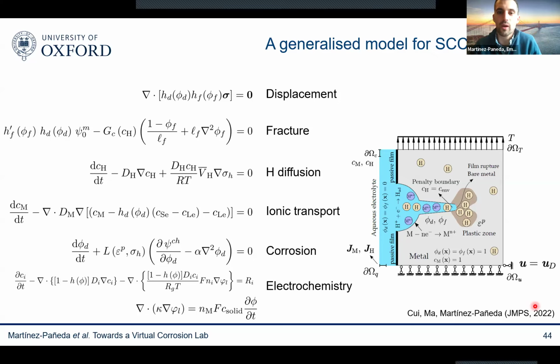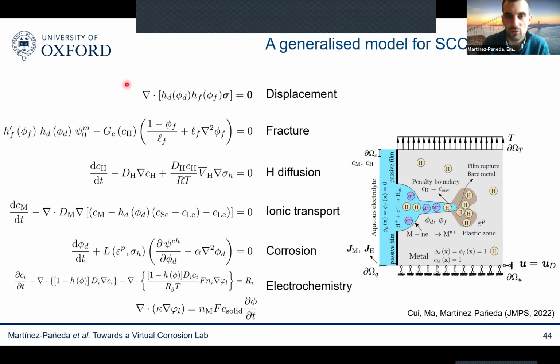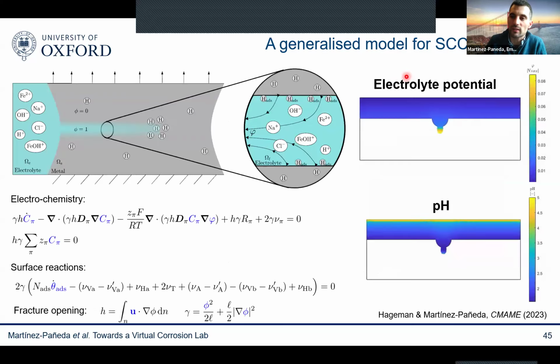So you can see here, we are now combining everything that I showed you before. So your mechanical problem, the ionic transport, electrochemistry, and corrosion, with also the fracture problem. So we have a phase field model for fracture, and also the hydrogen uptake and transport problem. So we're solving everything up there. And then when you do that, basically you can capture naturally the impact of the environment, whether it's anodic dissolution or hydrogen-driven mechanisms, and one combines with the other.